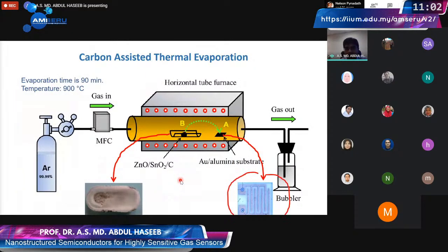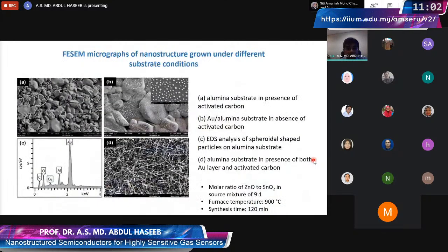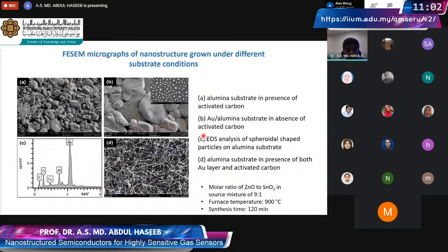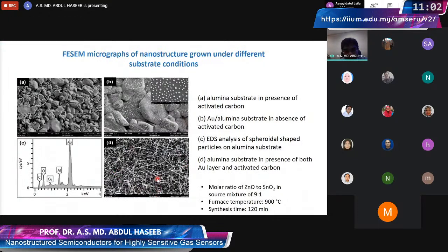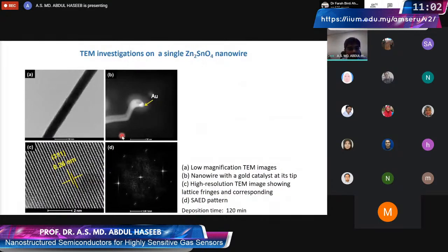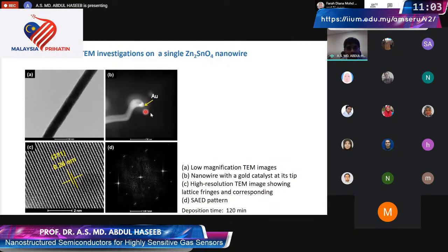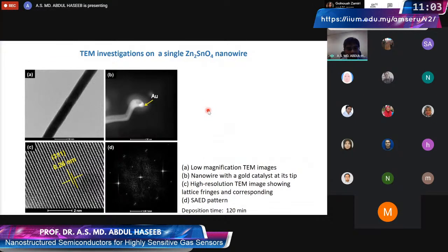Then we look at another place: the material that forms on our place of interest, which is the interdigitated platform for our sensors. When you look at the material that forms here, that is a big story, but I will cut it short. I just want to highlight this. We see that well-grown nanowires are forming, and there is a small tip on each of those nanowires. When we do further study, we realize that the tip is gold. You remember that we use a gold interdigitated substrate. The gold layer was already there, and it is taking part in this. We know there is a mechanism by which gold can catalyze nanowire growth.